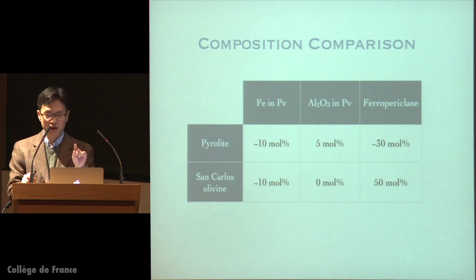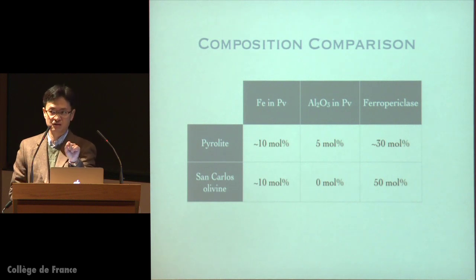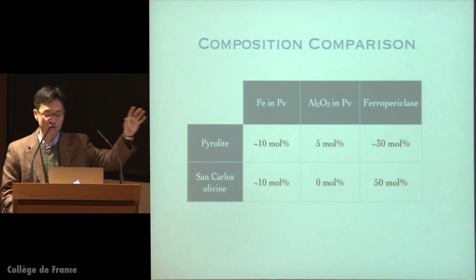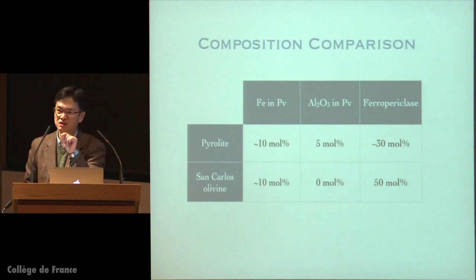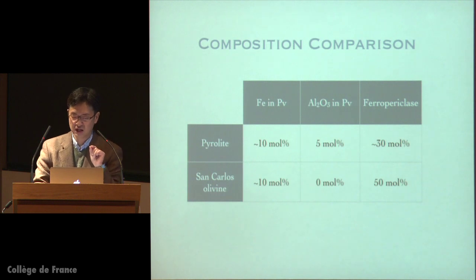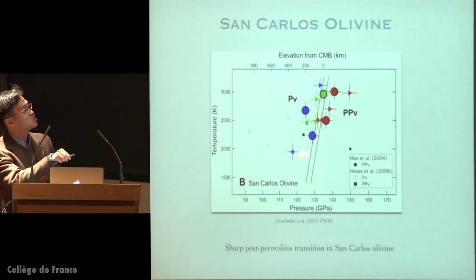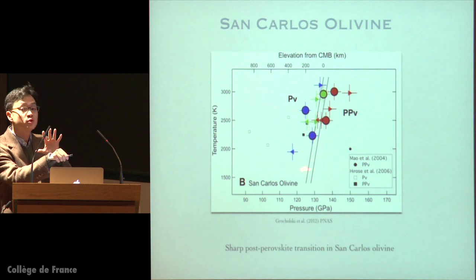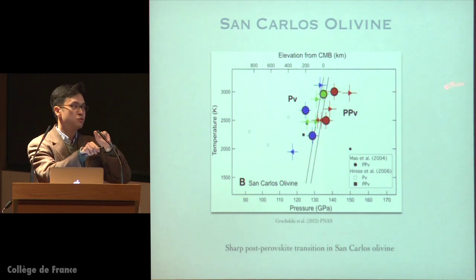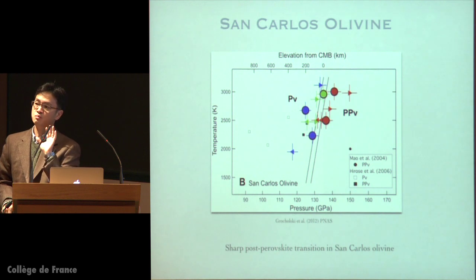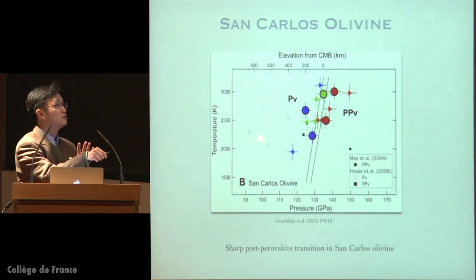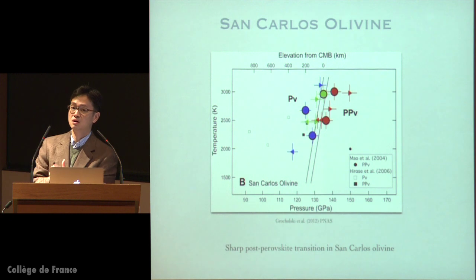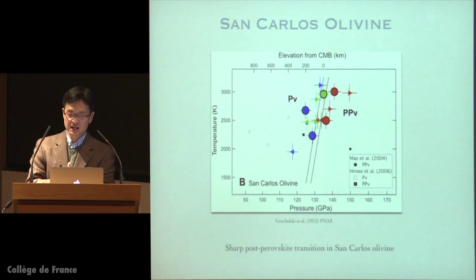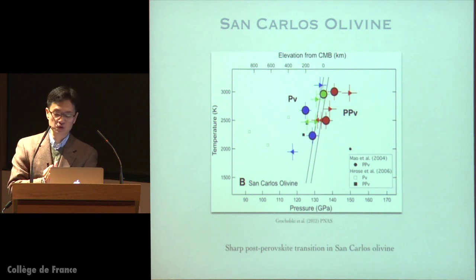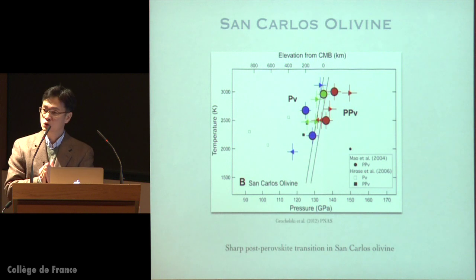So now what we try to do is to plug in ferropericlase in the system that was different from what we've done in 2009 and see if ferropericlase can change the thickness of the post-perovskite. And the convention is such that the blue represents, again, the pure perovskite, low pressure phase, and red represents pure post-perovskite, so high pressure phase, and green represents the observation of both high and low pressure phase, namely perovskite and post-perovskite.